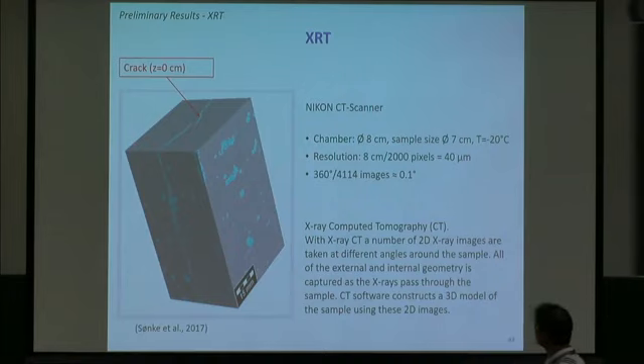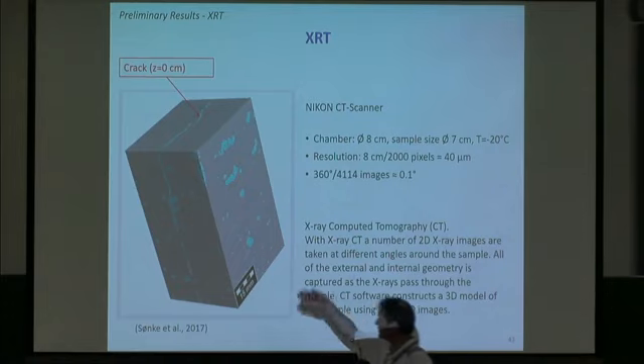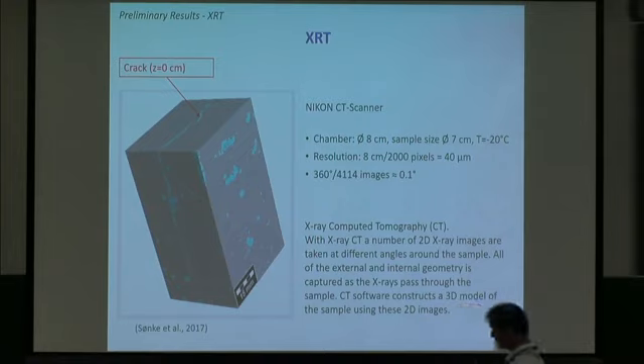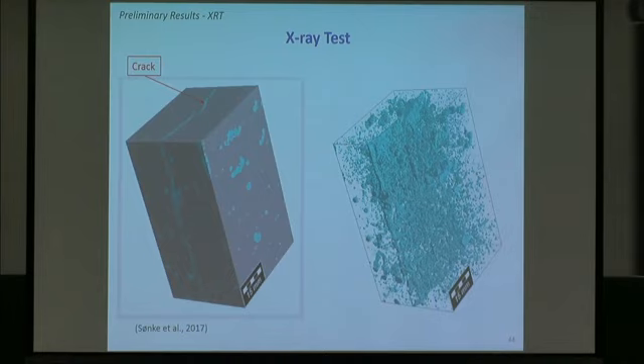We had access to a chamber here, diameter 8 centimeter, and a sample size in this case of 7 centimeter. We ran it at -20, and this is of course in the lab at home. And here we could slice up with 2D images which we put together into a surface which tells us something about the crack development and the crack surface. So by 2000 pixels here, we have a resolution of 40 micrometer. And the rotation here is then 0.1 degree for each slice we have in here. So from this, we could get a 3D model, as you can see here.